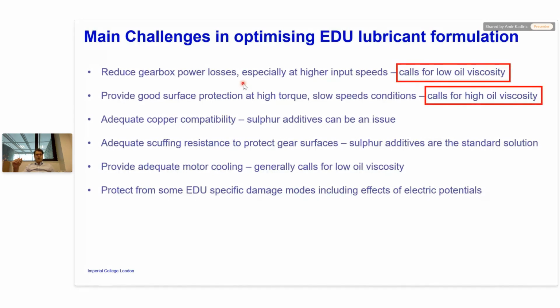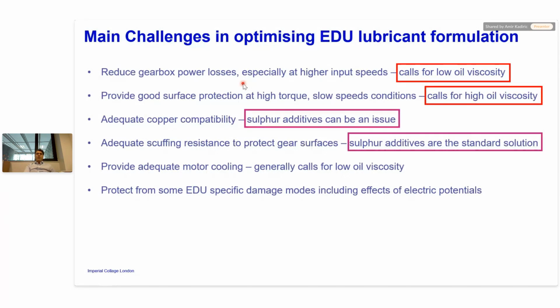It doesn't stop there, unfortunately. If you are using the same fluid to cool the motor and to lubricate the gearbox, you have to think about copper compatibility. So the sulfur additives can be an issue in that case. But these gears can also scuff. Scuffing is one of the most common gear failure modes. And if you have high loads, high speeds, scuffing becomes more likely. So sulfur helps in that respect. So you have this competing requirement of, do you put sulfur, do you remove sulfur, high viscosity, low viscosity? Where is the optimal? Clearly, you can't satisfy all of those at the same time.